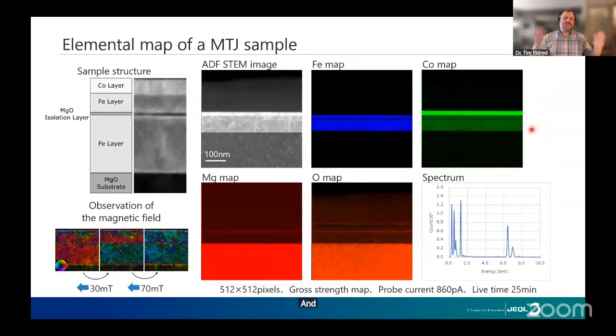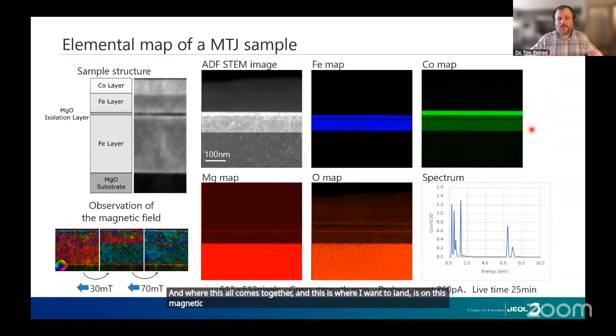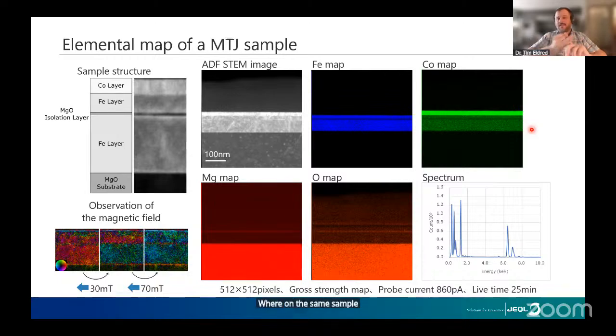And where this all comes together, and this is where I want to land, is on this magnetic tunneling junction sample, where on the same sample at the same time, we can map all of the elements that are around. We can do traditional imaging, but also we can apply magnetic fields. And in the differential phase contrast, we can see how the magnetic structure of the material changes with the application of millitesla fields.